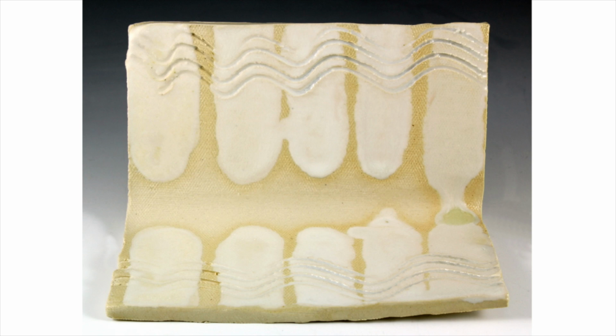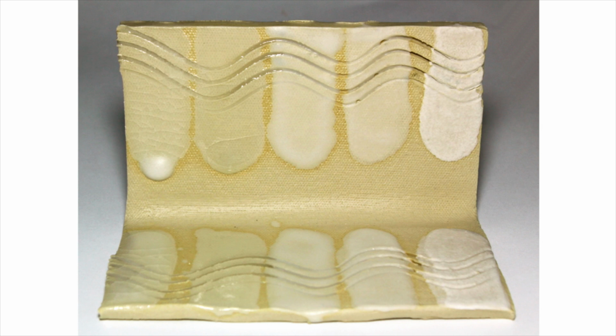Now, to make a glossy glaze go matte, or a matte glaze go glossy, take out the clay and add it back into the glaze in 5 to 10% increments. Note how the additions of EPK, the clay, can produce a matte glaze.